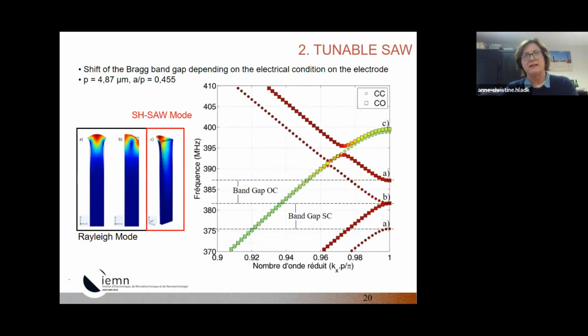Here you have the dispersion curve of the device I just presented. In that case, the goal is to have a filter around 400 megahertz. With this device, the period will be 4.87 micrometers, and A over P is 0.455. A is the thickness of the electrodes, P is the period. As you can see, depending on the electrical connections that you put on the electrodes on the top of the surface, you have different band gaps, short circuit here, and open circuit. So you have two different band gaps depending on the electrical connections. This is a very interesting result.